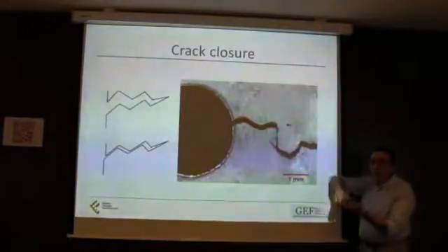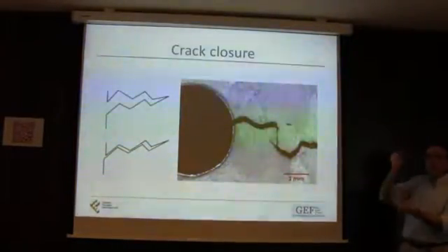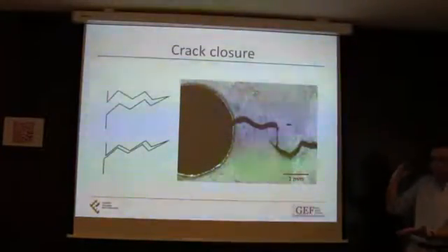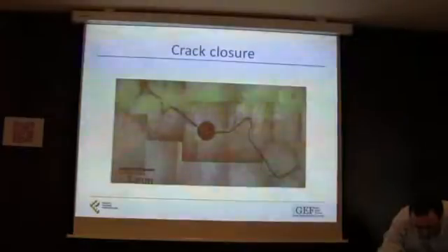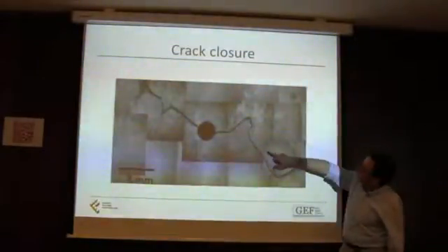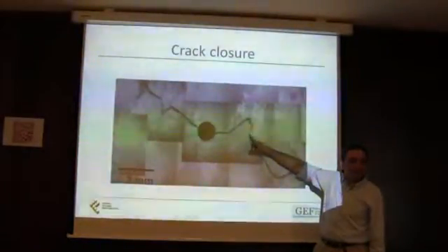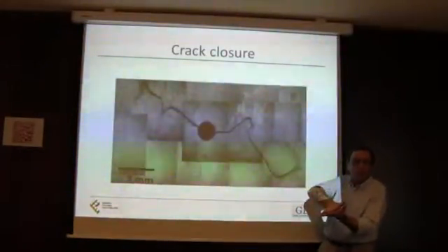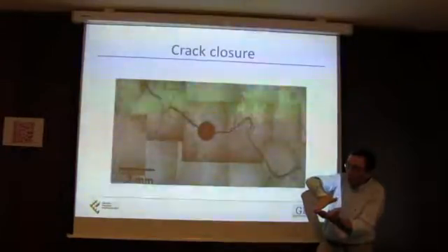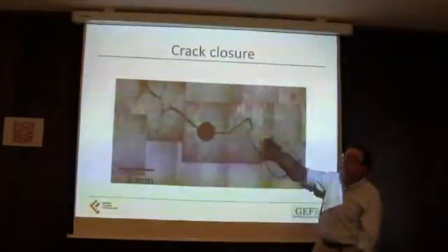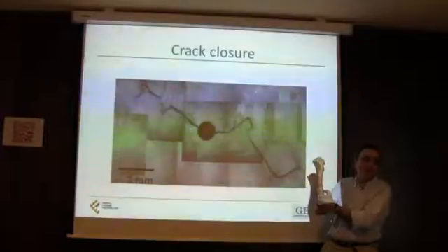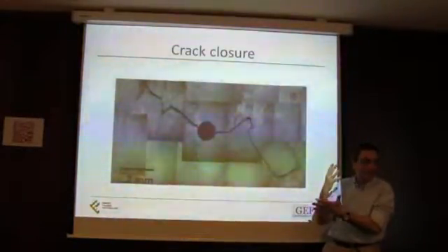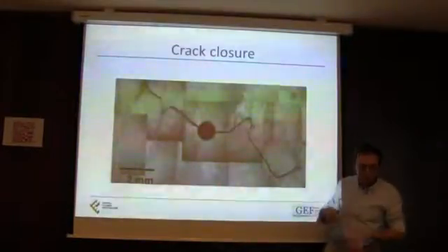So you can have some tensile stresses pulling the crack faces when you try to separate them, which is something that I find interesting. And look in here, you have the same. Can you see that? So it's not just that the crack faces are going to touch before the crack closes. It's that when you start applying load, these things will pull the crack faces and will refrain them from separating too early. It's like you have some kind of clutches there.